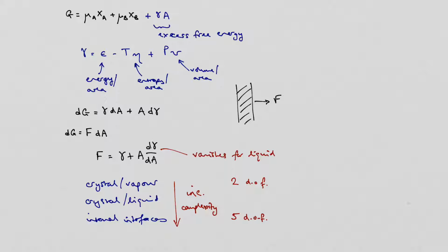So it will only matter when we have an awful lot of surface area in our system, when there's a lot of interface per unit volume, and that is when things are at a very small stage, when you've got lots of little things emerging from the soup. And this just goes back to nucleation theory.